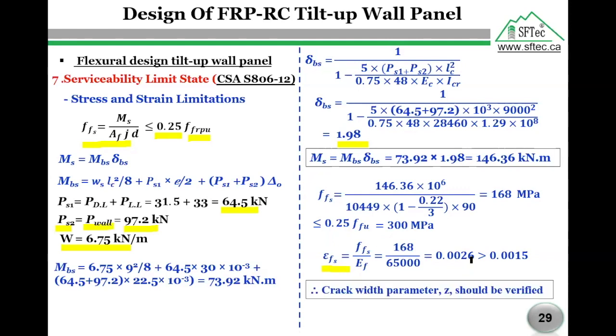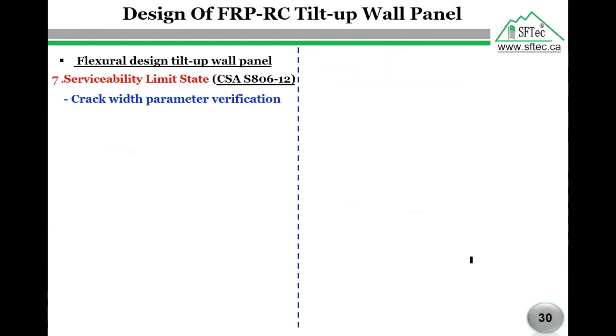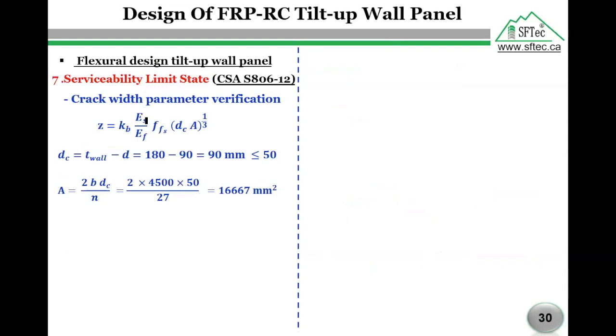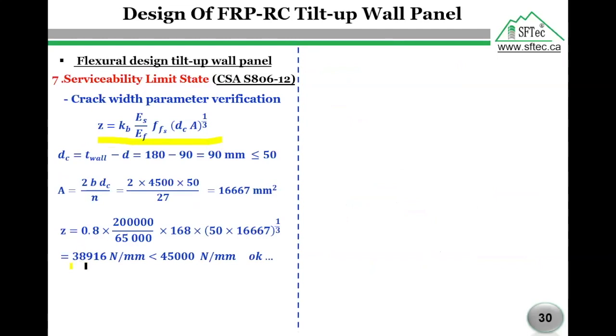When the maximum strain in the FRP bar exceeds 0.0015, the crack width parameter should be verified. So now we are going to check the factor Z. The crack width parameter can be calculated using this equation. So finally, we have Z equals 38,916, which is less than 45,000 Newton per millimeter. So we did a good job. We checked the serviceability limit state. We obeyed the maximum limits of the codes, so we are on the right track.